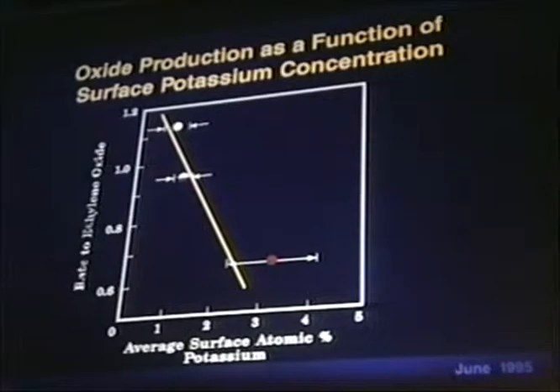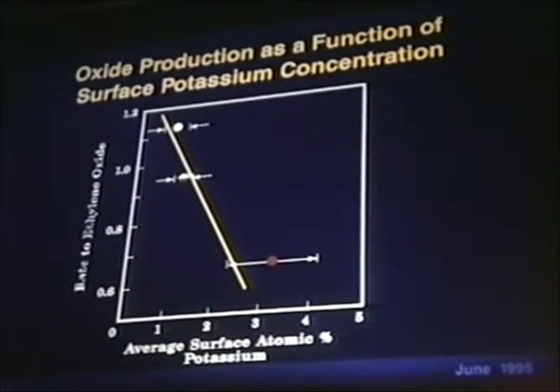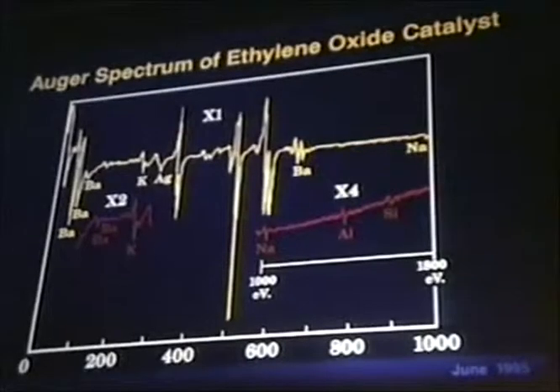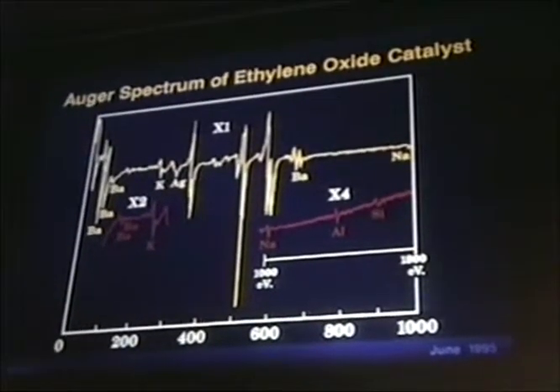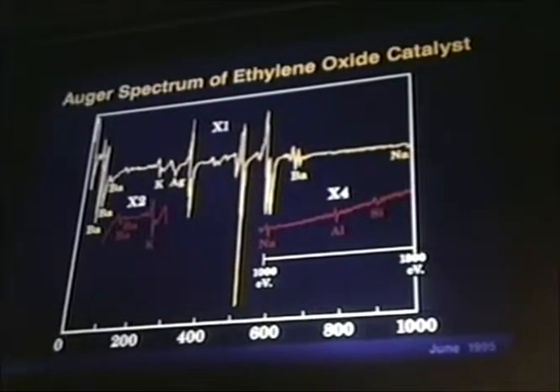In this graph, what I have summarized is the surface analysis, basically average surface atom percent based on scans over several areas and averaging them, and then the rate to ethylene oxide on the y-axis. Ethylene oxide rate was found to be, as you can see, inversely proportional to surface potassium concentration. In addition, we were able to, next slide, identify the presence of other impurity elements as well: sodium, aluminum, silicon, on the catalyst surface.